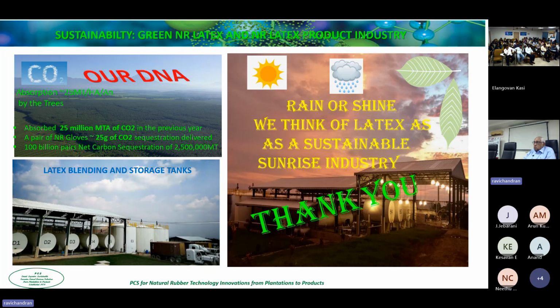Yeah, one of the problems earlier on was that the original formulations had natural rubber latex for nylon dipping. But latex stability in these high-speed dipping machines, because the fabric is running at such high speed, the development of coagulum was much higher with natural rubber. The synthetic rubber lattices are extremely stable because they've got a much higher content of soaps, and their particle sizes are smaller. They don't form coagulum that easily. Their mechanical stabilities are of the order of 3,000 as against natural rubber we get 800 or so, 1,000. Now with the ultra low floating, we have started getting mechanical stabilities of 2,000, 2,500.